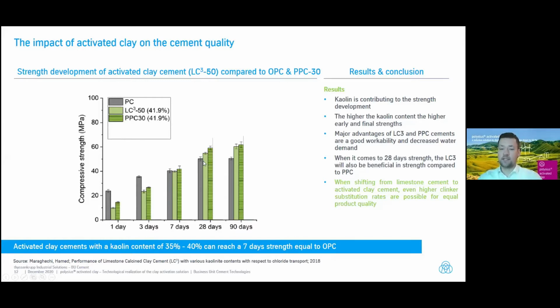And this is the reason why activated clay is pushed so hard in all markets at the moment. Everybody is talking about this one because it's a quite cheap substitute, and it is also giving some strength advantages. So limestone is just a filler. Activated clay is also giving some strength contribution at the end. So when we're talking about, for example, limestone cement substitution, then we can even go very low with the clinker ratio. So this has to be investigated for all cases in the lab. But we can imagine that the clinker content can be lowered to 40%. This can happen depending on your clay, depending on the clinker, etc. So this has to be investigated. But then for sure you will come up with a quality which is equal to limestone cement quality at the end.